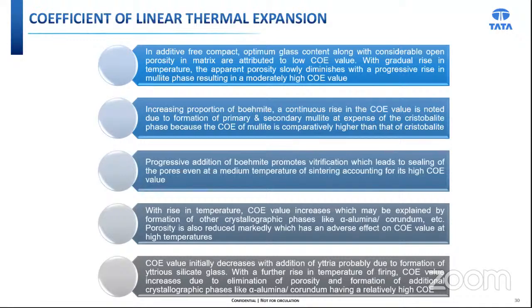The COE value initially decreases with the addition of yttria, probably due to the formation of yttrium silicate glass. With a further rise in firing temperature, the coefficient of expansion value increases due to the elimination of porosity and formation of additional crystalline phases like alpha alumina (corundum), having a relatively high coefficient of thermal expansion.